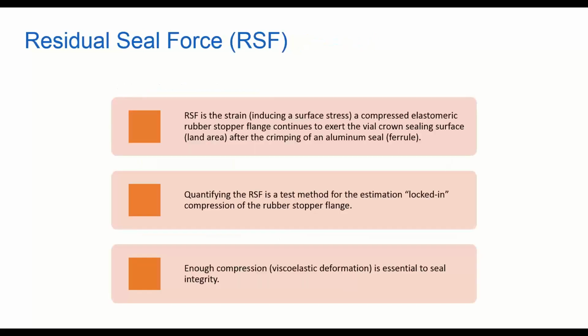Go ahead and advance one more time. So we do that by measuring residual seal force, and RSF is the strain, the surface stress a compressed elastomeric rubber stopper continues to hold on the sealing surface of the vial after the crimp is in place. That number will vary over time. There is some degradation that you see. There are other factors that cause some stress relaxation. Likewise, as the temperature goes down, residual seal force goes down. When the temperature is restored, the residual seal force is also restored. So quantifying RSF is a test method that estimates the locked-in compression of the rubber stopper by measuring that energy in that locked-in compression. Enough compression is essential, of course, to seal integrity, and even more significant compression is necessary to hold CCI at those low temperatures.